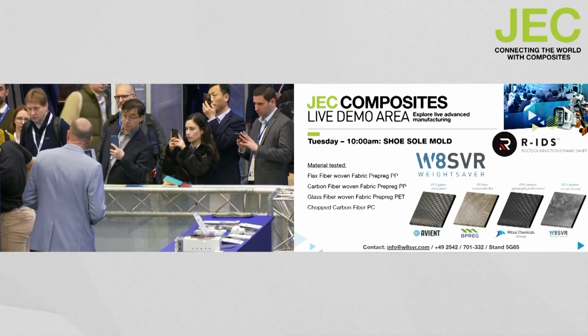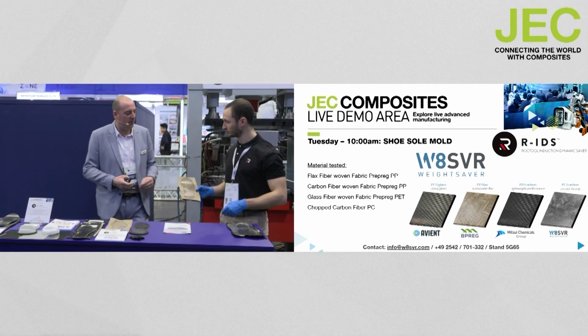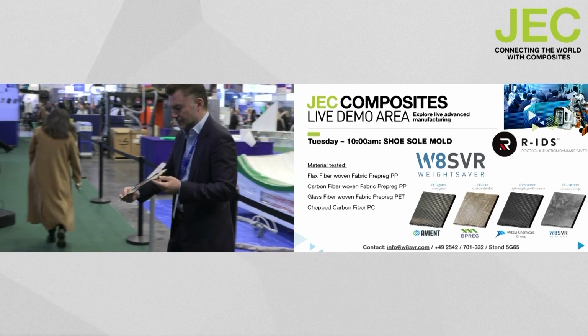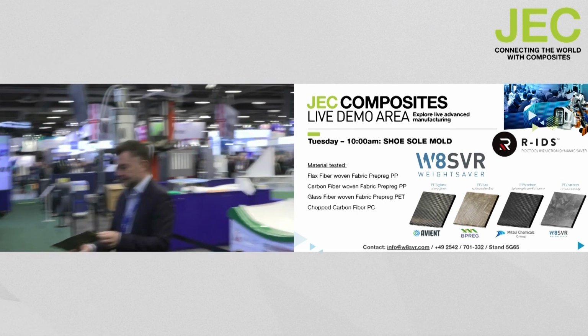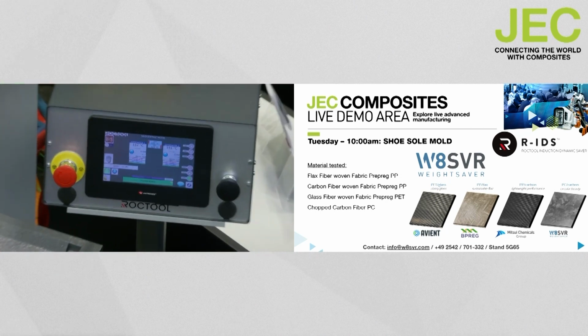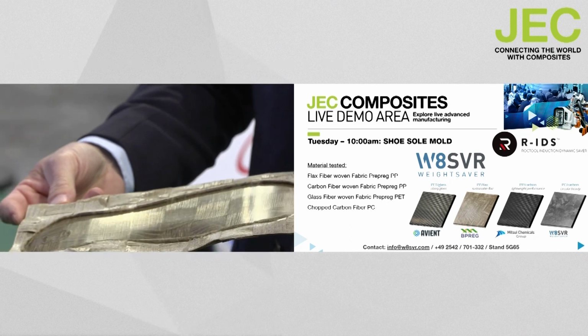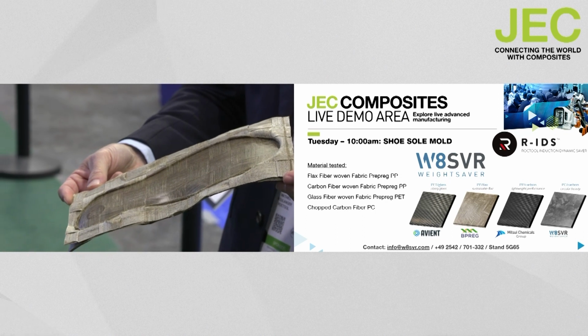So you see here, we finalize the part and we open the press to demold the part. As you see, we have consolidated the part in just a few seconds, also without degradation of the natural fibers, which is a difficulty when transforming thermoplastic composite material with flax fibers. Thanks to our technology, the induction heating and the very quick cycle, there is no degradation of fibers and we can consolidate this innovative material with very good surface quality.